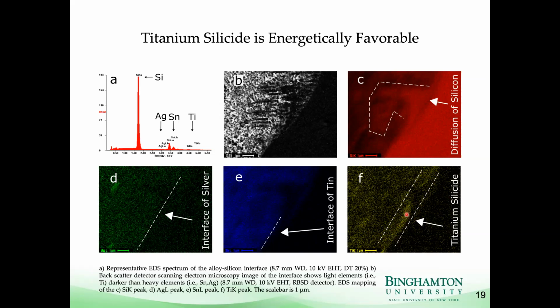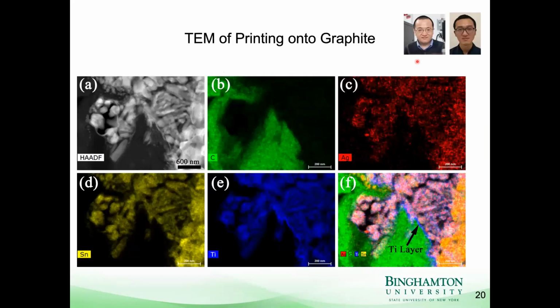We have done transmission electron microscopy. So my colleague, Professor Zhou, and his grad student Xiaobo did some transmission electron microscopy, elemental mapping, and this is the interface. So this was on a slightly different material system. This was on carbon that has the same metal alloy printed on top of it. So this green here is the carbon layer, sorry, the carbon film.